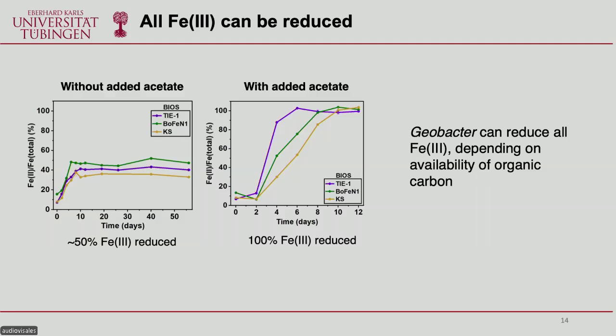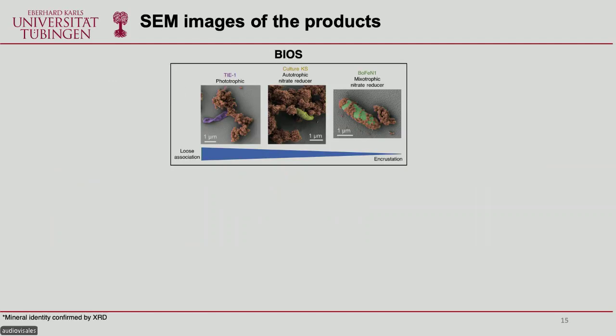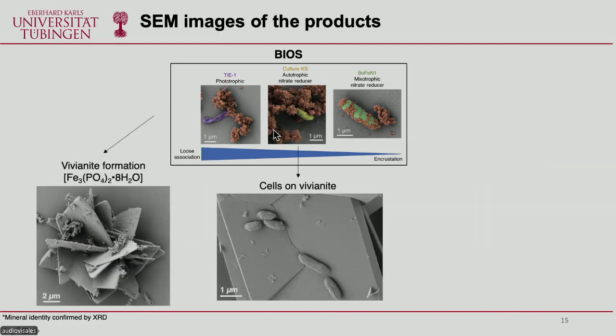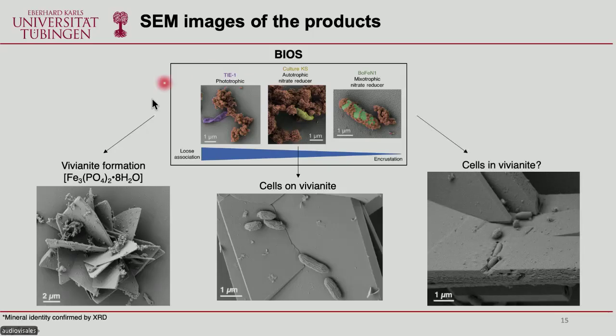But what's more interesting is that when we then look at the transformation products under scanning electron microscopy, we had these 3 different biogenic iron oxyhydroxides, and for the first 2, more or less, we see the same thing. We saw the formation of vivianite, which is an iron 2 phosphate mineral. They have this characteristic blade-like tabular structure. And we saw a lot of cells on the vivianite, mostly those with these characteristic ridges that we think are Geobacter.